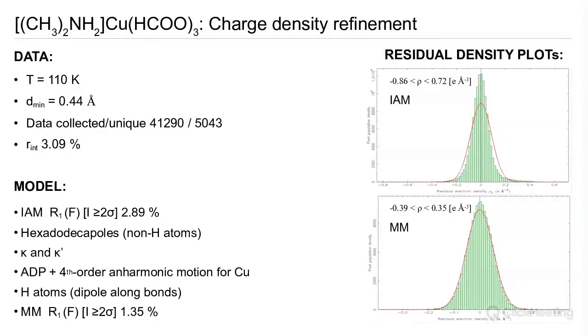So can we go deeper into the nature of this exchange interaction? We did this through a charge density refinement. There was a plot similar to this in Piero's talk, looking at the residuals. The data were collected on a laboratory source, if I remember correctly, something of the order of 41,000 reflections measured out to a resolution of 0.44 angstroms. If we use just a conventional independent atom model, we find an R factor of about 2.89.